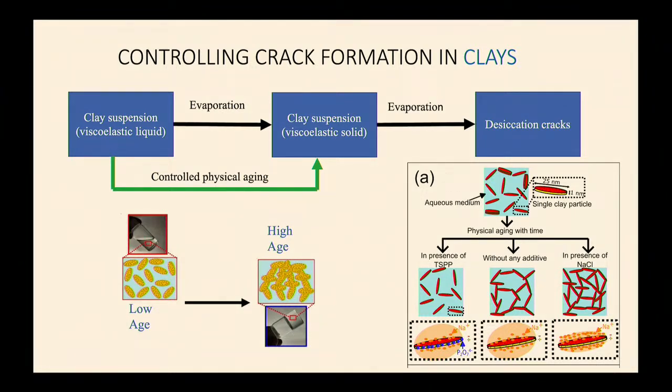And that completely fluidizes your system over the experimental time scale. And of course, there was the second experiment where we did not use any additive at all. So you got the usual clay gel, and in the third experiment, we put common salt. And remember I told you these clay particles have a Debye layer around them. So when you add the salt, you're basically shrinking the Debye layer.